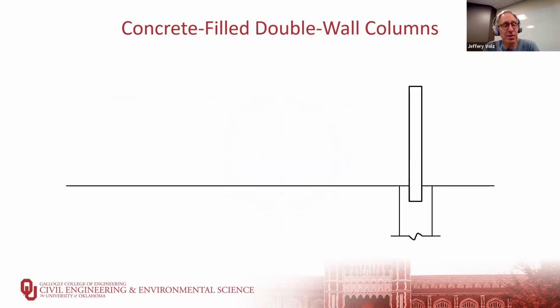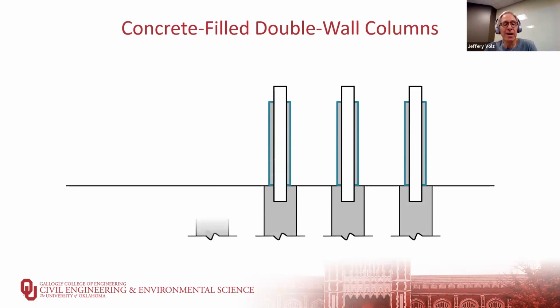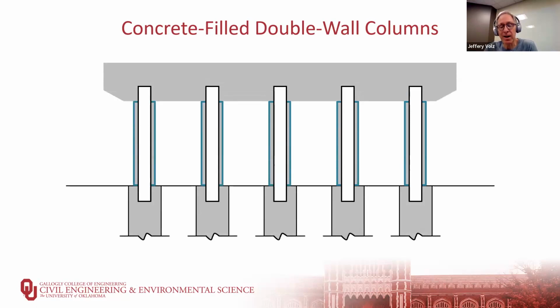Place the steel tube into the foundation, and it could be a drilled shaft or it could be a spread footing. Place the concrete in the foundation that then anchors the steel tube. Drop the FRP tube over the top, and then fill the annular space between the steel tube and the FRP tube with concrete. Then once you have a number of piers, a number of columns, you can then erect the pier cap, form that, and add the reinforcement.